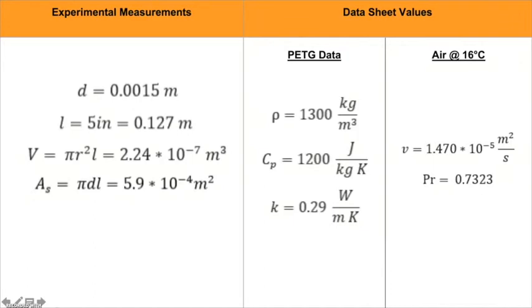The diameter of the extruded PETG filament was held at a constant diameter of 1.5 millimeters. The length at which the filament completely hardened was located 5 inches away from the extruder nozzle. With the length at the steady state and the diameter known, the volume and area were then calculated to help determine the thermal resistance and the capacitance, using the calculated convection coefficient H, and from the published datasheet values for density ρ, specific heat capacity Cp, conductivity K, the kinematic viscosity for air nu, and the Prandtl number Pr.